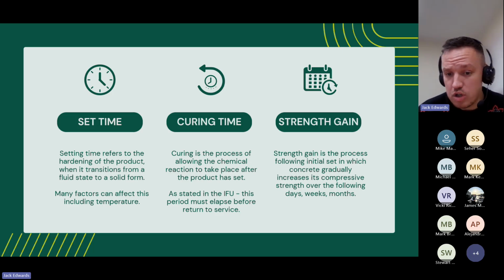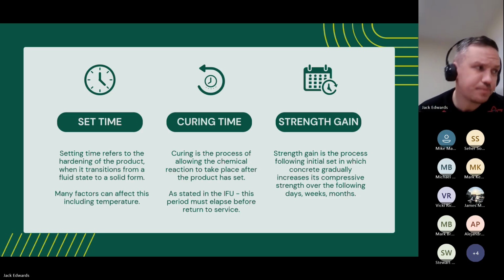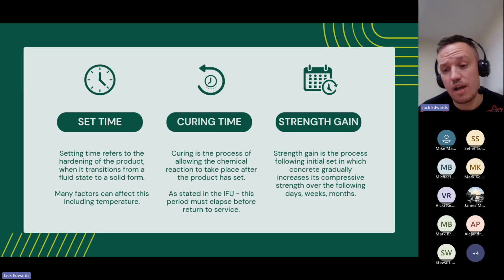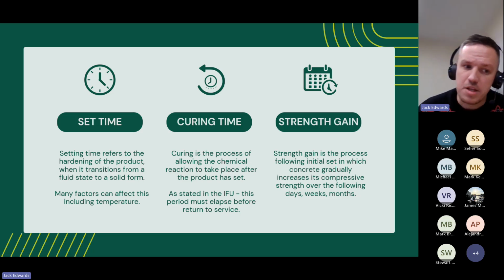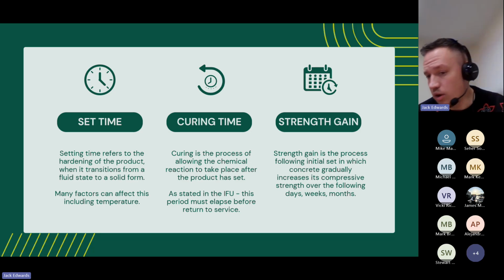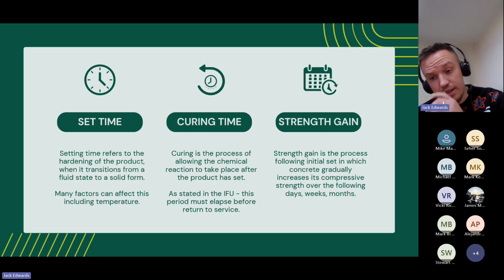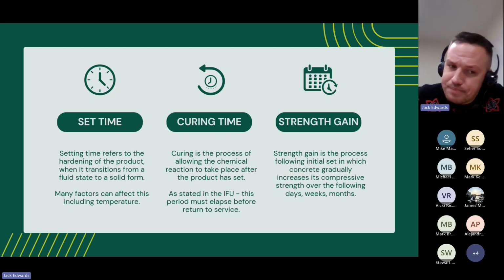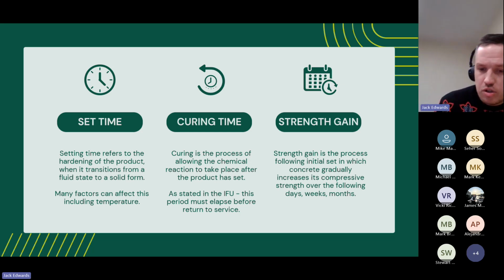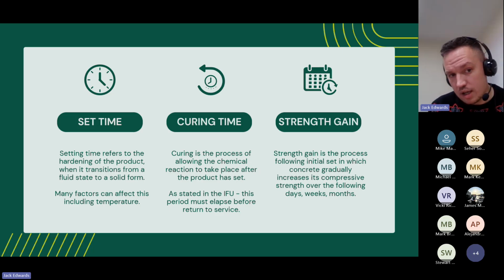So with the temperature, obviously we're talking about working in lower temperatures. The temperature will affect the set time of the product. So in lower temperatures, the set will be longer. In higher temperatures, the set will be quicker. So as I mentioned a couple of slides ago, in low temperatures, by using warmer water, that will accelerate the setting time to make the initial set quicker.